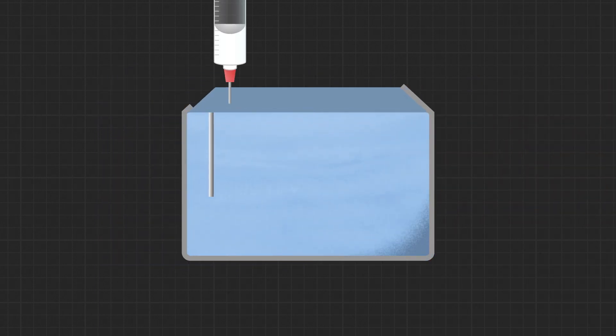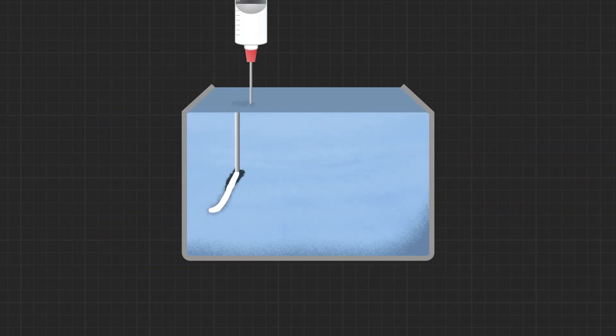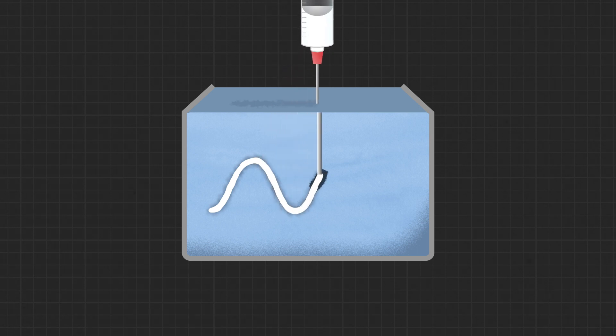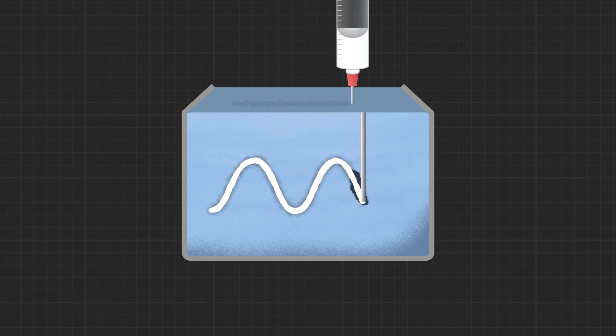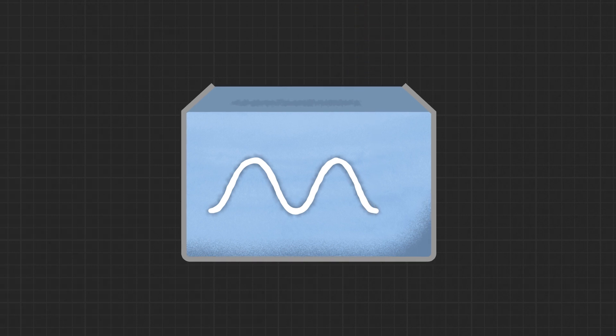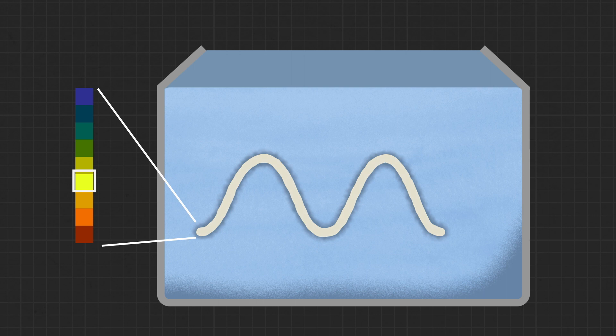LIFINK is printed directly into this slurry, which traps the bioink and cells in place as you print. This allows taller, thinner structures to be created. When printing with the acidic LIFINK, the buffered solution serves to neutralize the ink immediately upon printing.